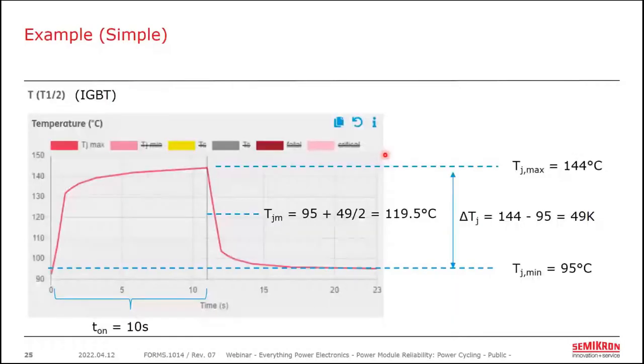So in this example, we have a balanced three-phase inverter, so we only need to look at either one diode or one IGBT. And for this particular condition, where we're driving a resistive load with unity power factor, the worst case happens to be the IGBT. So that's what I'm showing here. And what we see is that the IGBT is at 95 degrees under that steady state 125 amp condition. And we hit it with that 200% step load, and the junction temperature rises up to 144 degrees.